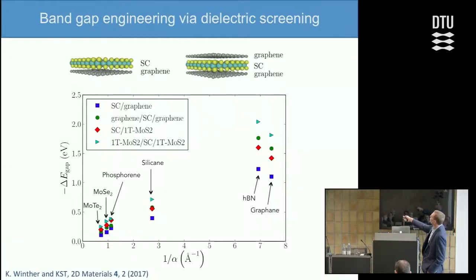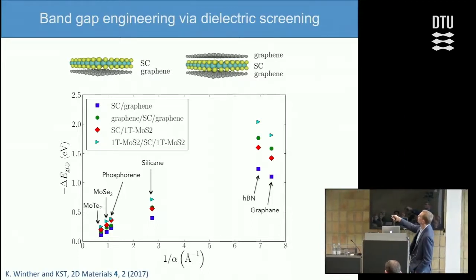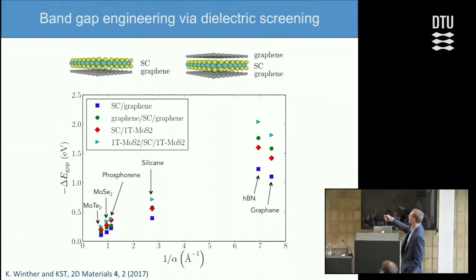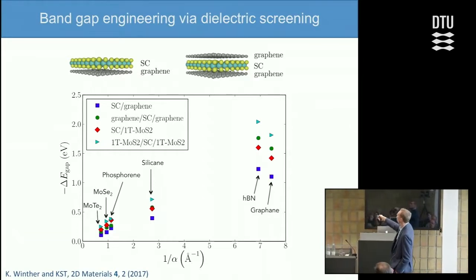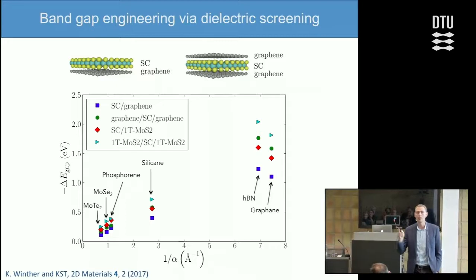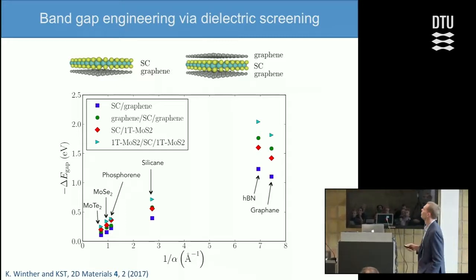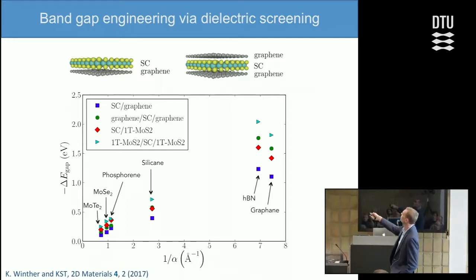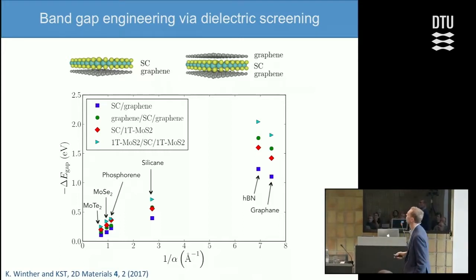Here you can see the calculated band gap of different semiconductors when they are embedded in two layers of graphene. The point here is that we can really tune the band gap quite significantly by modulating the dielectric environment, by embedding the semiconductor in different types of two-dimensional materials.